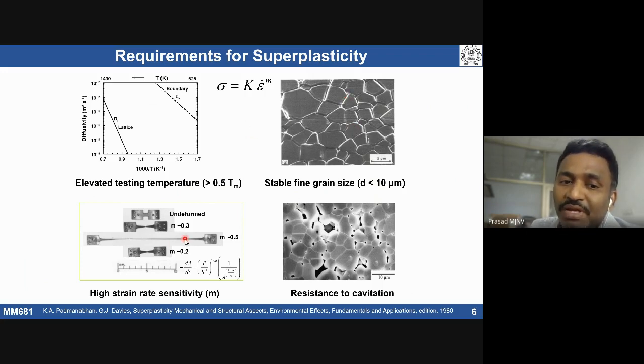The material should exhibit high strain rate sensitivity. The m value should be as high as possible. The higher the strain rate sensitivity, the closer we get to Newtonian viscous flow. m equal to 1 means the stress exponent is equal to 1, which means we can have viscous flow. So that means resistance to flow localization.